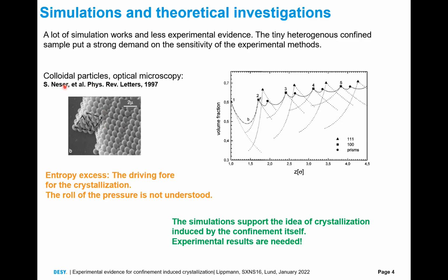Nevertheless, I show you here one combination of experimental work and simulations where crystallization of colloid particles is proved under an optical microscope. The simulation shows that with decreasing gap size, different crystal phases can be observed. Another thing I want to point out is that theoretical investigation shows that crystallization should happen due to the entropy excess. But all experimental works show that pressure plays a very important role in confinement. Therefore, the role of pressure is still not understood in this process.